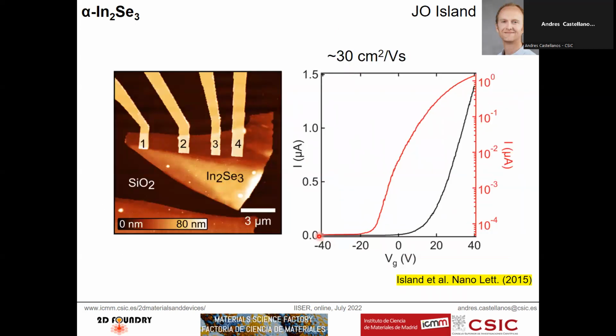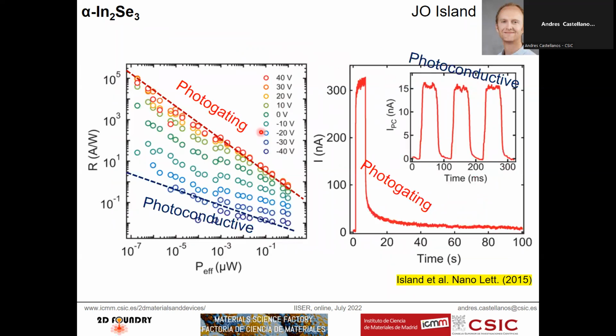Okay, so for negative gate voltages, the current is negligible, it is in the off state. And when you start applying positive gate voltages, then you start turning on the semiconducting channel. So you start populating it with more and more electrons. And what we see is that this responsivity can be tuned from being generated by the photoconductive effect to the photogating effect. Okay, in the photogating effect, you get this very steep slope and very large values.